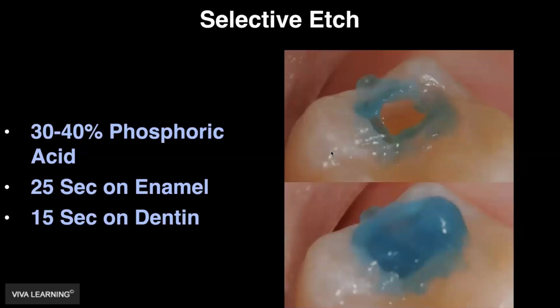An alternative way to use phosphoric acid is a technique that we call selective etching. So selective etching lets us put phosphoric acid on the enamel first. Then we're going to just go to 10 or 15 seconds. Then we're going to finally cover the dentin portion of the tooth preparation. We're only going to leave that phosphoric acid on the dentin a max of 15 seconds. Science today would say 10 seconds is adequate. And then we're going to rinse it and dry it all simultaneously.